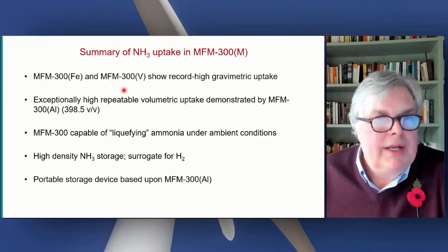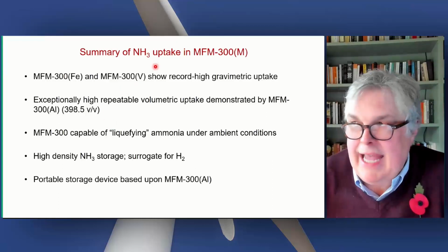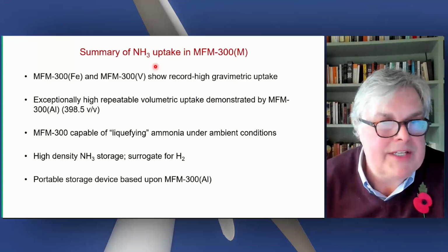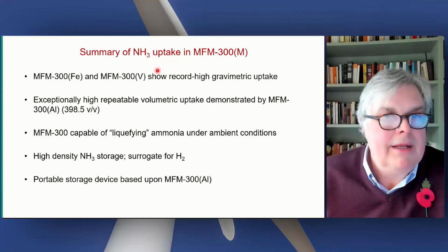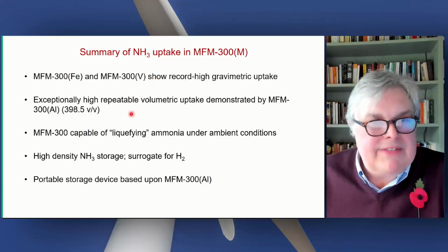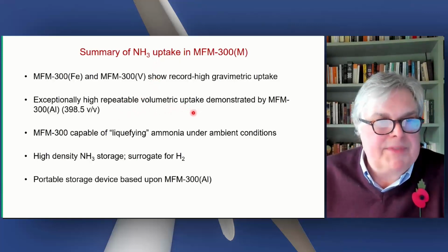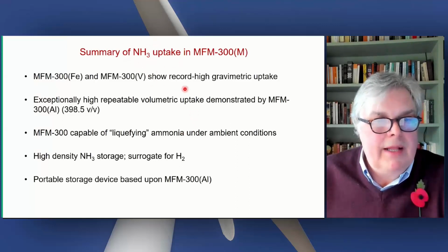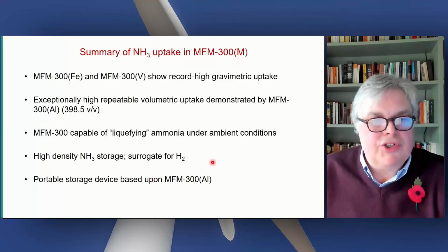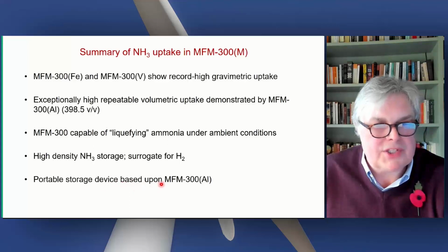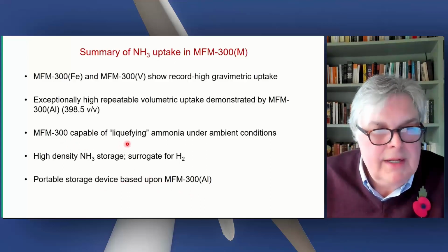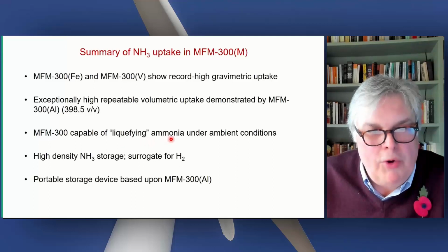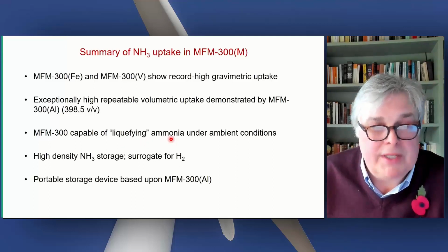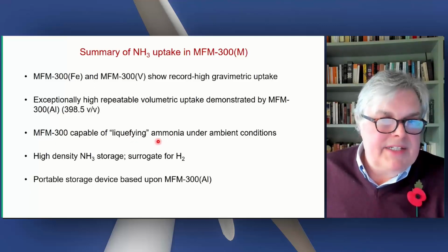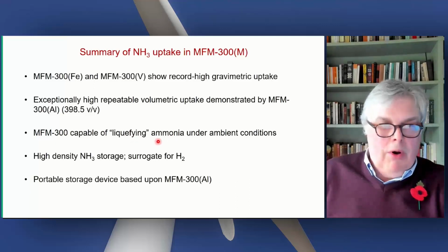So we've managed to not simply take a highly acidic NO2 or SO2, we've also done this with a highly basic corrosive ammonia system as well. It's very repeatable, very high volumetric uptakes. And of course, the next step is to look at chemical reactions of ammonia, linking that into the release of dihydrogen, and of course, using this as a mobile store for ammonia, because the actual density of ammonia within these MOFs is extremely high. And we have one system now that is approaching the density of solid state ammonia within a pore at room temperature.